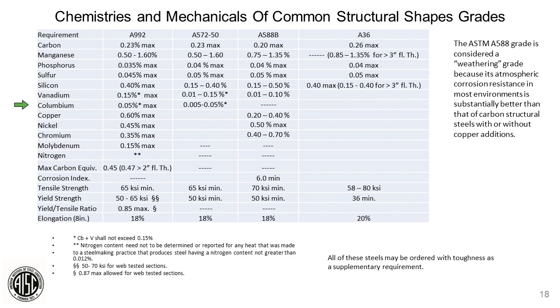You look at copper. Copper again is residual. We try to keep that down. A992 has a 0.60 max. 588, now this is where it's a little bit different. 588 is weathering grade, so copper must be within a range to maintain the corrosion effect, the corrosion protection that we're trying to put into the steel.